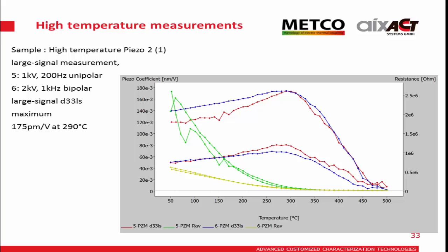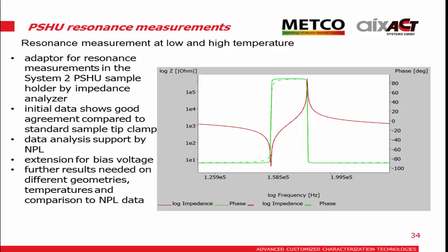This is the alternative. And this is just one slide, the resonance measurements. So we did also some resonance measurements in the same sample holder, so that you can compare resonance and large signal measurements within one setup. And it nicely agrees with the free mounted sample and in the sample holder. But so far it's only for the in-plane modes, because of the contacting, it will have an influence on your D33 in that case. So it's used for D31 and KP measurements.